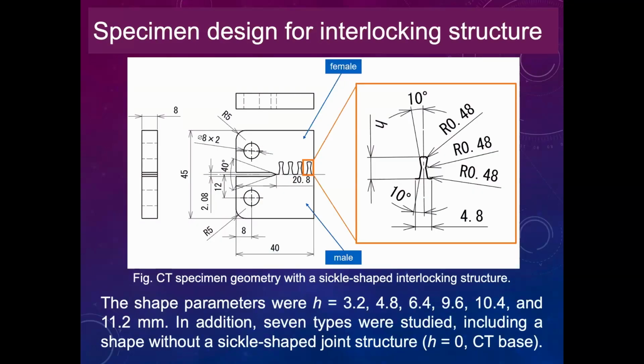First, we want to show you the CT specimen geometry with the sickle joints ahead of the artificial crack as shown here. This is the CT specimen, and this is the sickle joint part. Then we printed this kind of sickle joint for these cases.